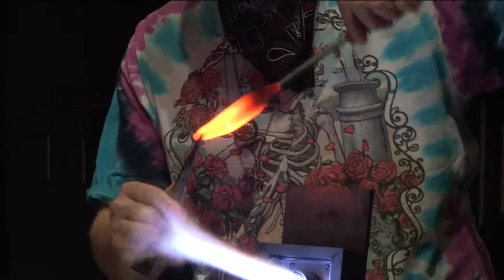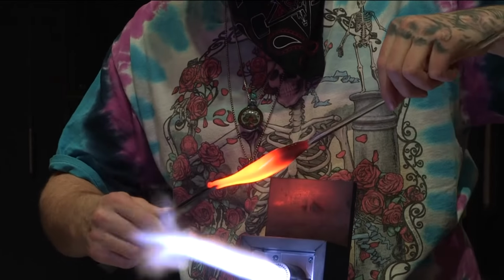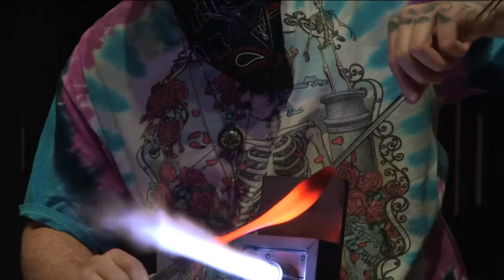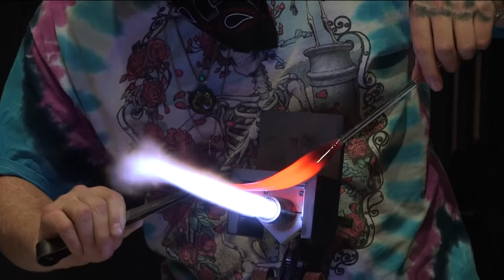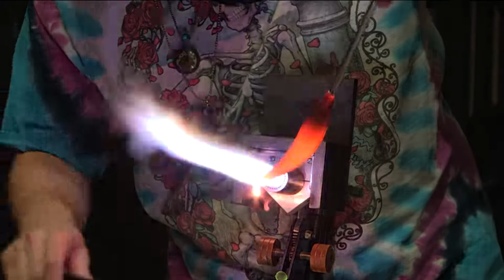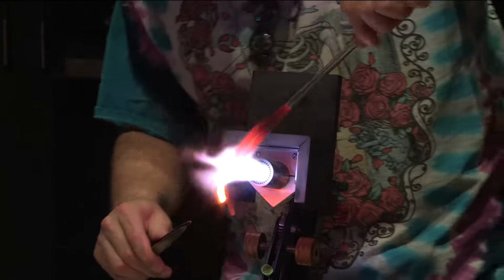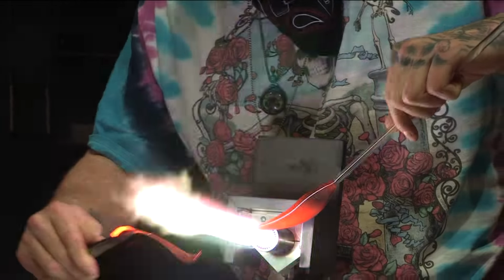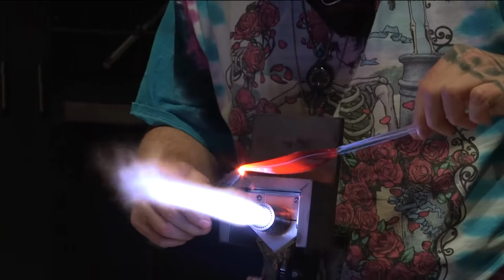So a big part of it, glass making in general, is all about timing and temperature. Anytime you have thin parts attached to thicker parts, the thin ones are going to cool much faster than the thicker ones. So it is very important to balance temperature as you go along. And these guys balance temperature in either of two ways.